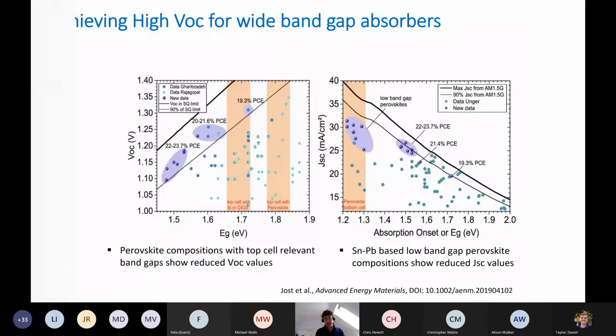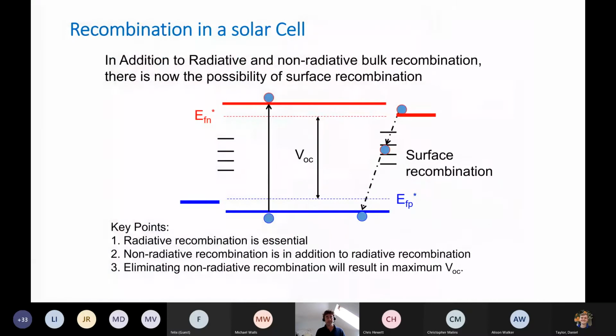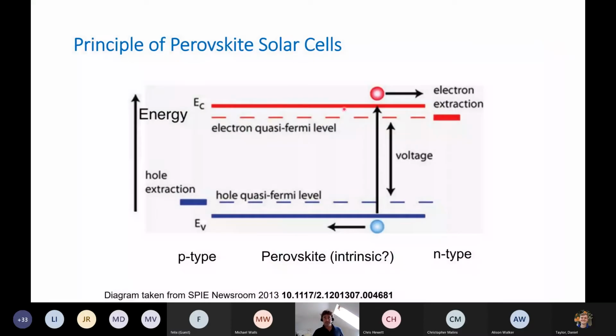We call that quasi-Fermi level splitting, and I'll come back to this term shortly. In a perfect solar cell, the extraction layer or contact will only allow one charge carrier type to move, in this case electrons from the conduction band. It would reflect holes, and there'd be no voltage loss or energetic drop between the quasi-Fermi level in the absorber layer and the contact material, and likewise on the hole contact.